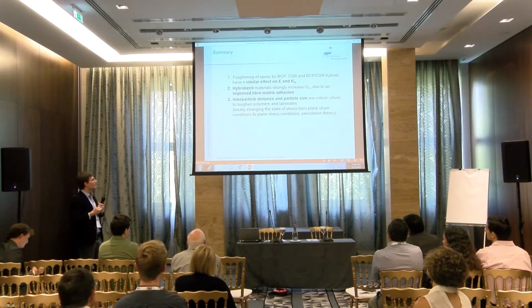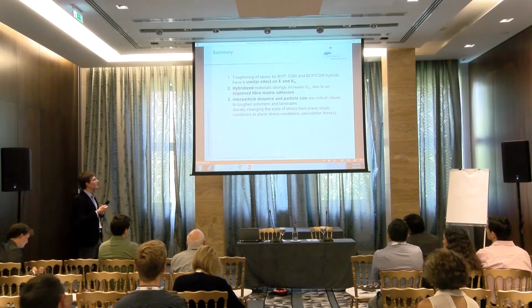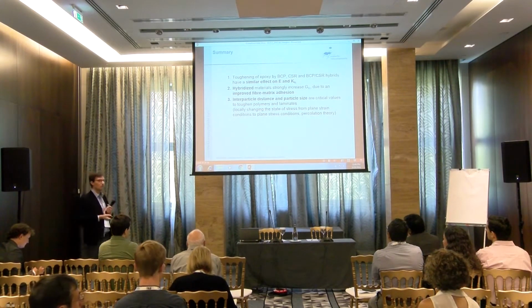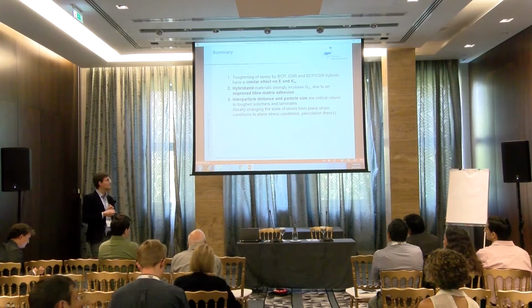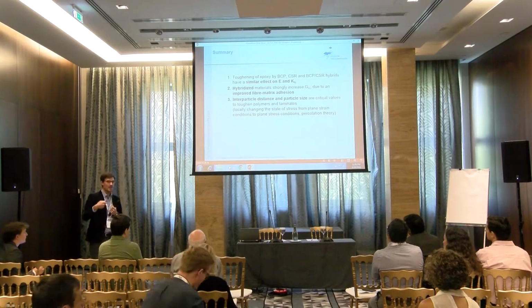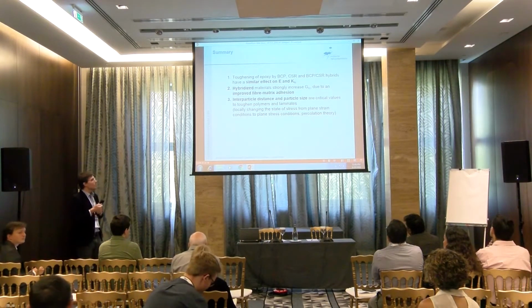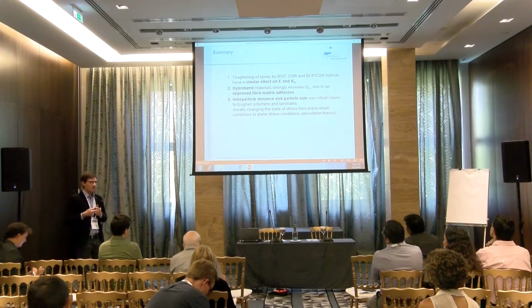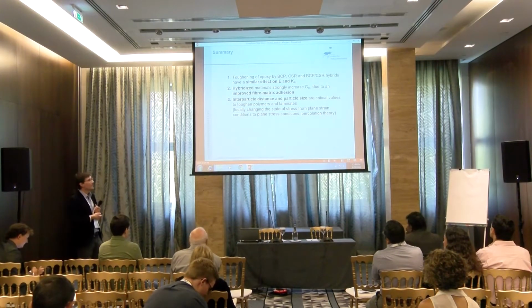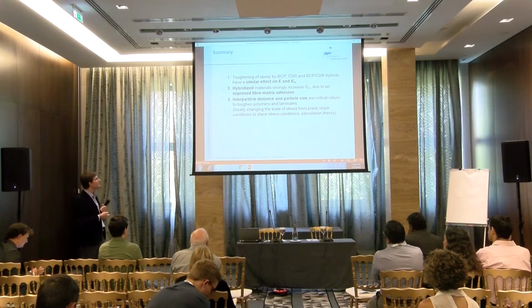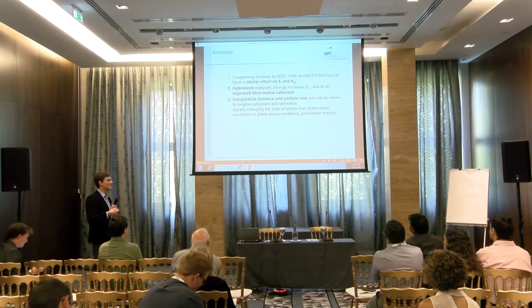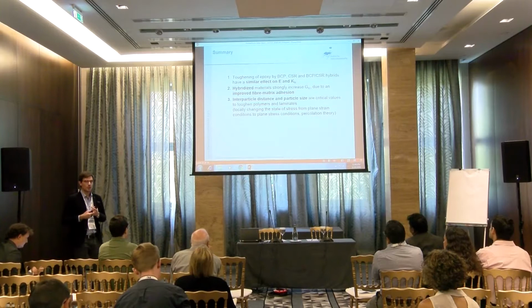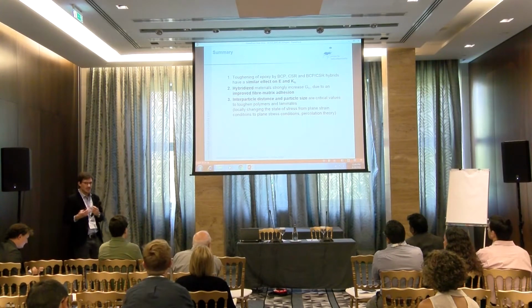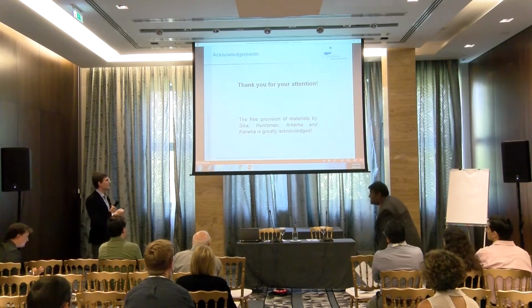So the results of this study: we have a similar effect of block copolymers and core-shell rubber particles on your stiffness and on the fracture toughness. We have, due to the hybridization, an improved fiber matrix adhesion, and the interparticle distance and particle size ratio are important properties to be considered for further processing or further research in that area. Yeah. Thank you very much.